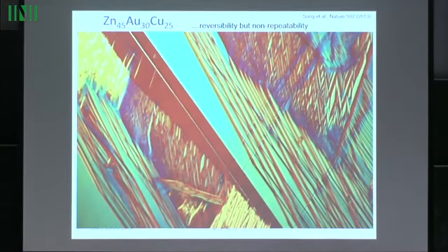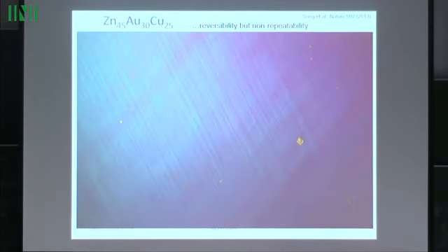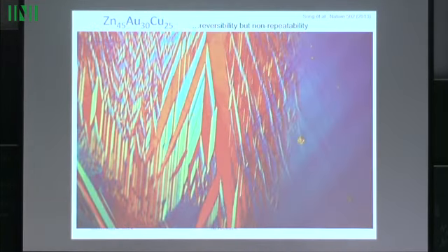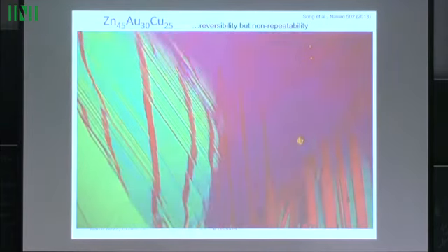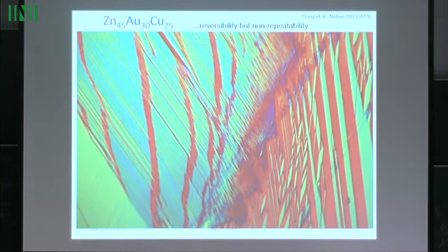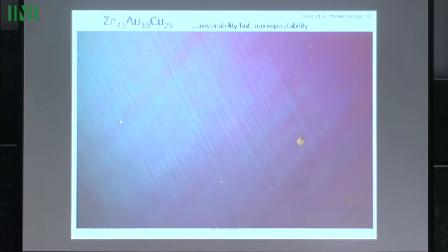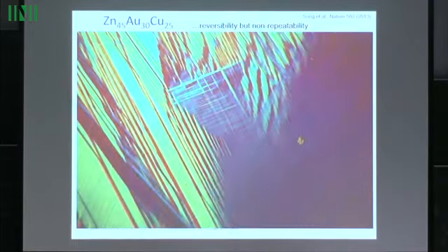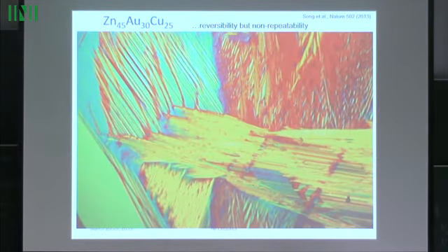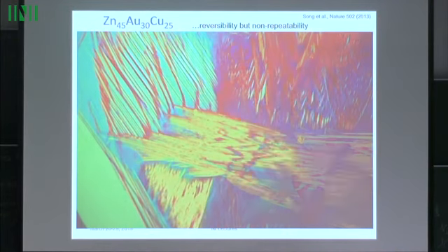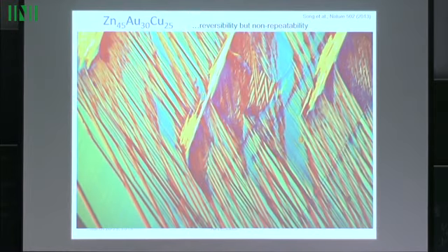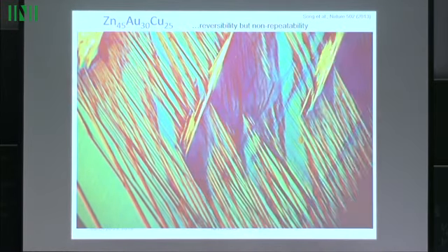So it's fun to look at what it looks like when you transform. This is a thin plate of the cofactor alloy. That's the martensite. It's being heated and cooled. That's the austenite, and it was being heated and cooled in such a way as to try to make the temperature as uniform as possible. Of course, it's not easy to do that because it has such small hysteresis. There's bound to be some biasing, and that's why you see that the interface moves more or less diagonally.